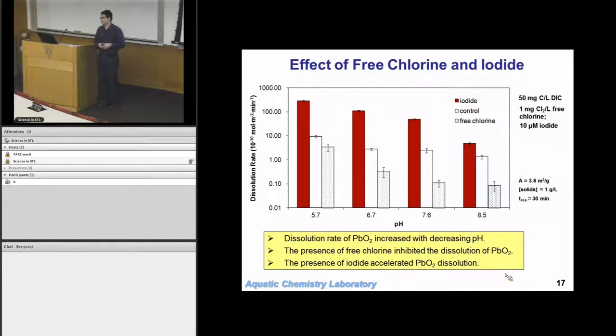Ultimately, they were able to solve this problem, not by going back to free chlorine, but by adding some phosphate. And phosphate helps make the lead, even the lead in the plus 2 oxidation state, less soluble. They adjusted the pH to an area where the phosphate would work very well, and that is how they have solved it.